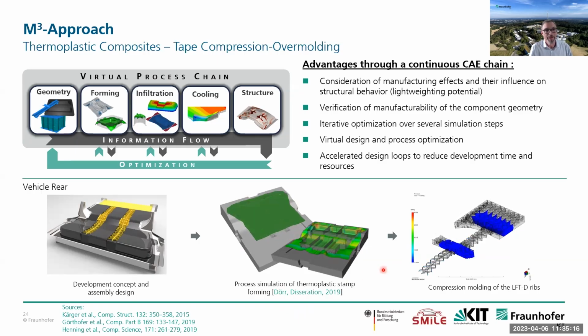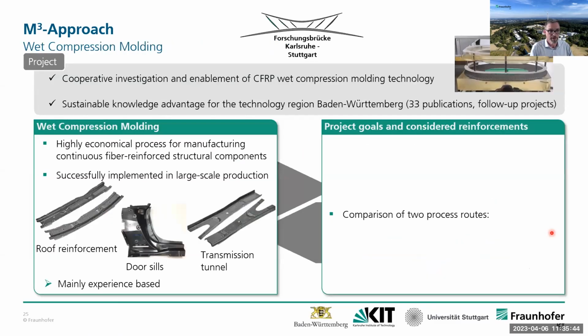wrinkle-free preform. And then this is, together with the aluminum longitudinal carriers, crash carriers, being inserted in the mold, and then it's overmolded by a discontinuous fiber reinforced thermoplastic, which already also joins the material at the same time to this part. Two examples where this holistic M³ approach has been applied, and I want to go a little bit more into the detail with wet compression molding.